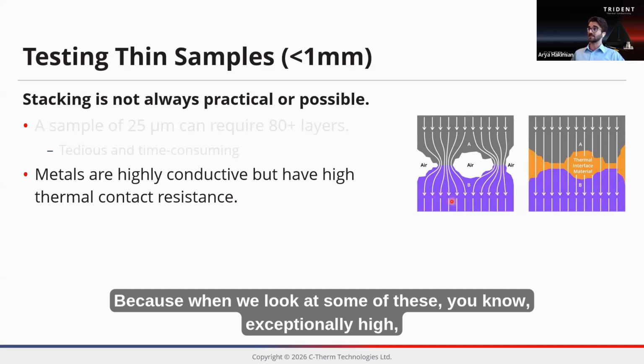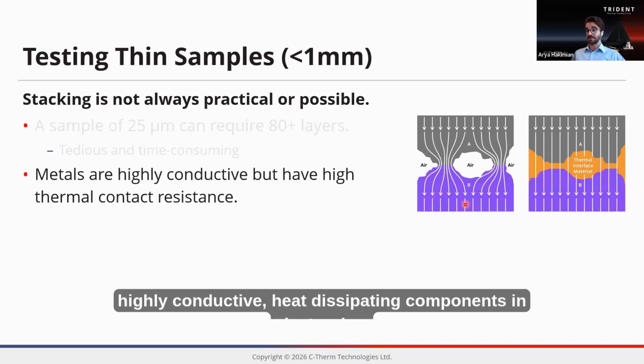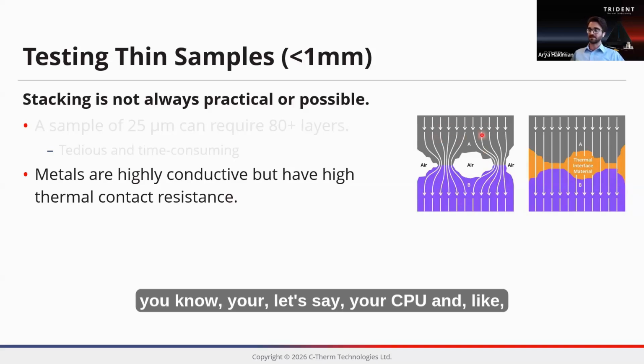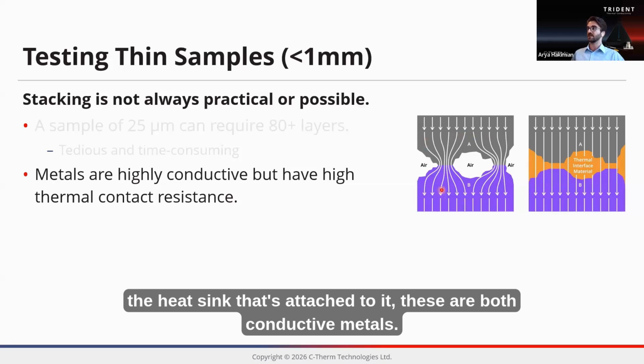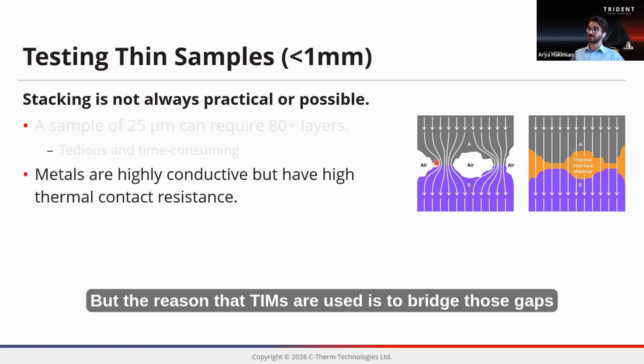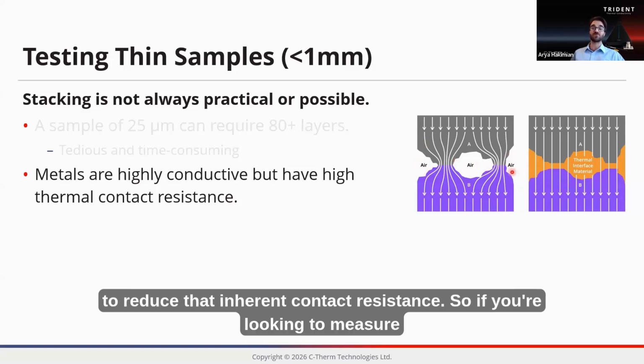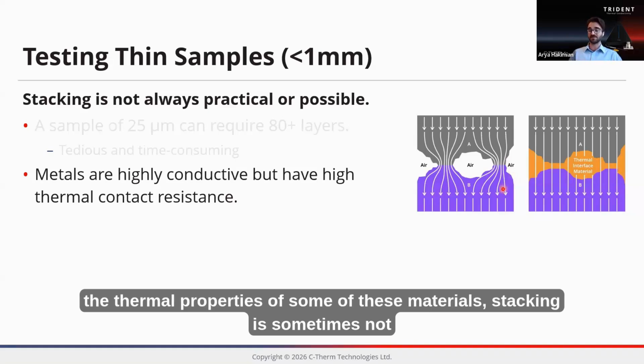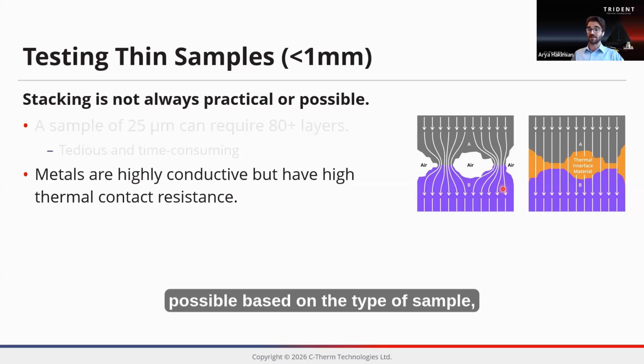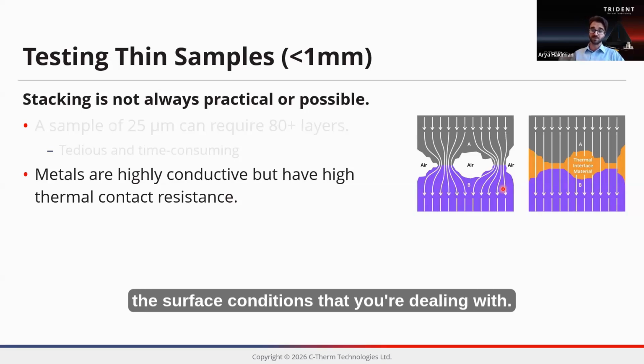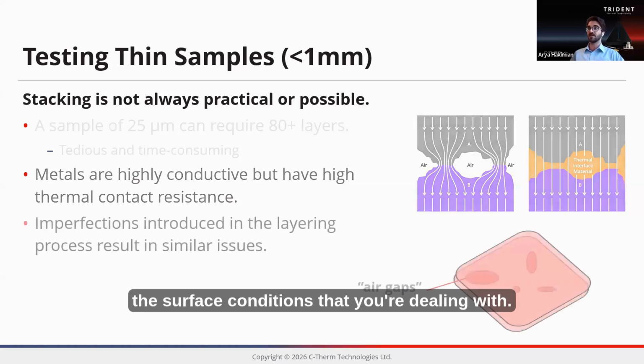Because when we look at some of these exceptionally highly conductive, heat dissipating components in electronics, let's say the CPU and the heat sink that's attached to it, these are both conductive metals, but the reason that TIMs are used is to bridge those gaps to reduce that inherent contact resistance. So if you're looking to measure the thermal properties of some of these materials, stacking is sometimes not possible based on the type of sample, the surface conditions that you're dealing with.